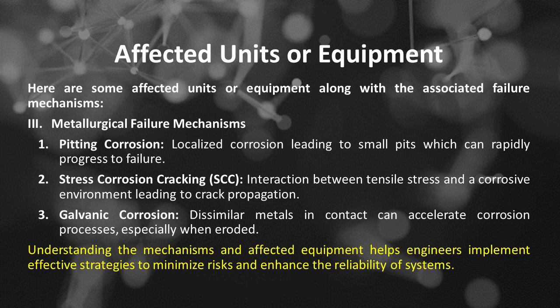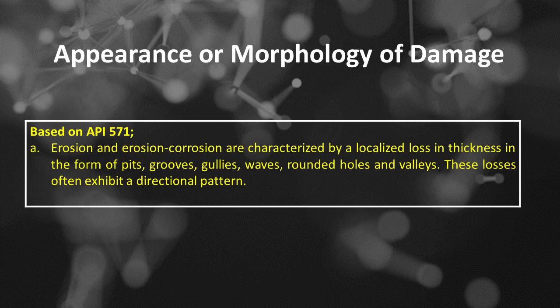Understanding the mechanisms and affected equipment helps engineers implement effective strategies to minimize risks and enhance the reliability of systems. The appearance or morphology of erosion and erosion-corrosion damage based on API 571. The first is erosion and erosion-corrosion are characterized by a localized loss in thickness in the form of pits, grooves, gullies, waves, rounded holes and valleys. These losses often exhibit a directional pattern. The second is failures can occur in a relatively short time.